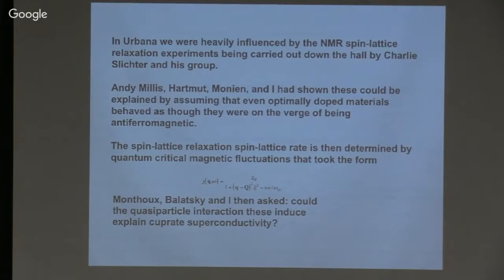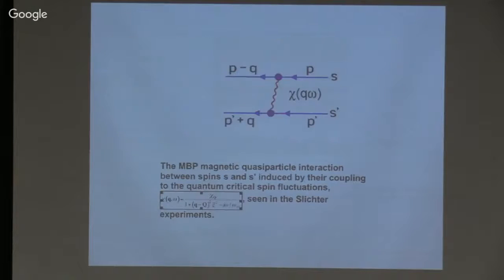And they're given, the spin-spin response function is given at the bottom part of the next slide. And you can show that you can see these quantum critical fluctuations very clearly in the NMR spin lattice relaxation rate. You get a good fit to what goes on with that particular response function. So what we did in Urbana was say, let's then ask, what does the effective interaction look like? It'll be just proportional to that spin-spin response function. And this is what it looks like. That's the magnetic quasi-particle interaction between a pair of spins.